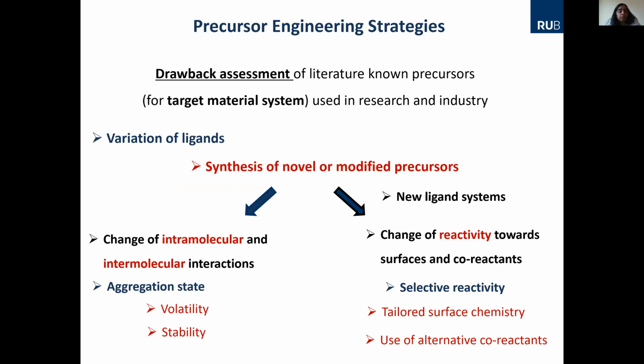So what is the main motivation? As I said, we want to make new materials or improved materials using CVD and ALD, and the basic parameters of precursor. So you may ask me, why do you want to make this precursor? Actually, there are several precursors known and they're commercially available, but each of them have pros and cons. So what we do is basically we assess the drawbacks of the existing precursors, because some of the precursors are not really good. You just take it from the cupboard and then you try it, but it may not work.